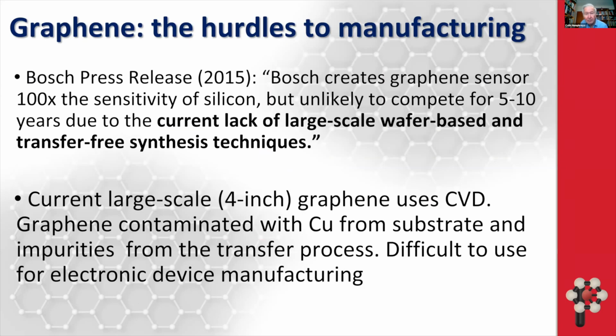And when Bosch made their graphene Hall effect sensor 100 times as sensitive as silicon, they issued this press release, which they said they created this sensor, but then they added these words in their press release. This is unlikely to compete for 5 to 10 years with existing sensors due to the current lack of large-scale, wafer-based and transfer-free synthesis techniques.